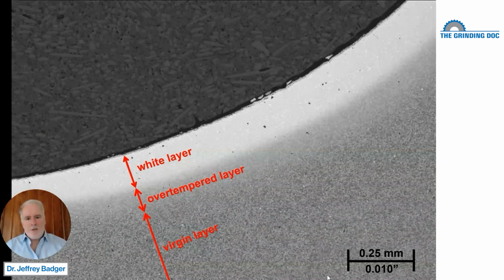And then you have all the issues associated with white layer, and that is a weaker material, a brittle material, a material that's going to have a shorter fatigue life, a material that doesn't hold coatings as well, a material that's more likely to crack, a material that's more likely to chip. Bad things happen when you get white layer. But fundamentally, white layer is just a recrystallization of the iron molecules, iron carbon molecules, face-centered cubic, body-centered cubic, and therefore we have a different phase of material.